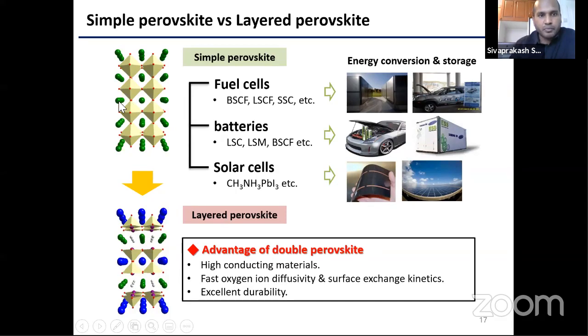What is the advantage of simple perovskite compared to layered perovskites? Compared to simple perovskite, layered perovskite shows high oxide ion conductivity, fast oxygen diffusion, surface exchange kinetics, and excellent durability. High conductivity gives fast conduction of oxygen ion, fast oxygen exchange diffusion, and the surface exchange coefficient improves the oxygen reduction reaction even when we decrease the operating temperature of the fuel cell at the cathode, and it shows excellent durability—meaning there is no degradation even after maintaining over 3,000 or 6,000 hours of operation.